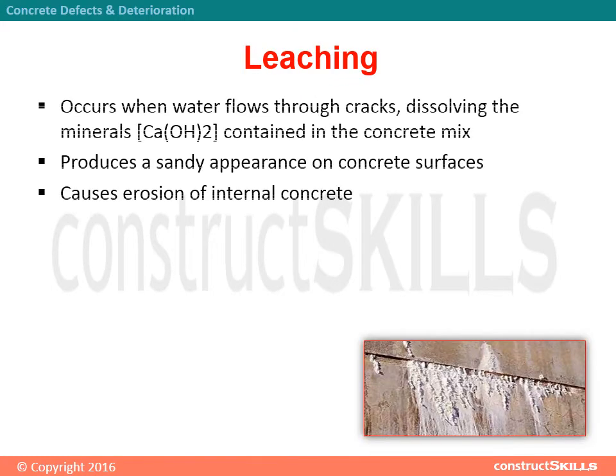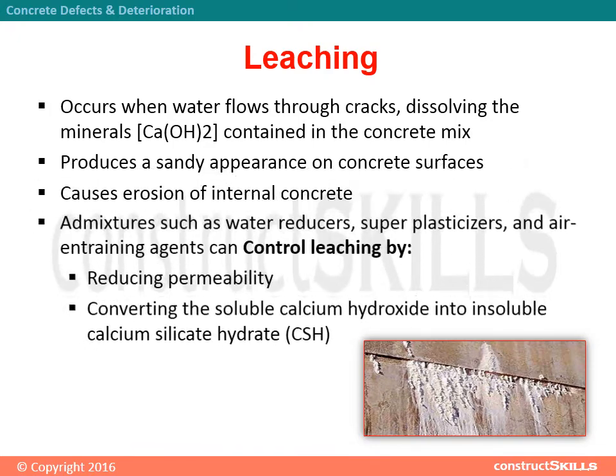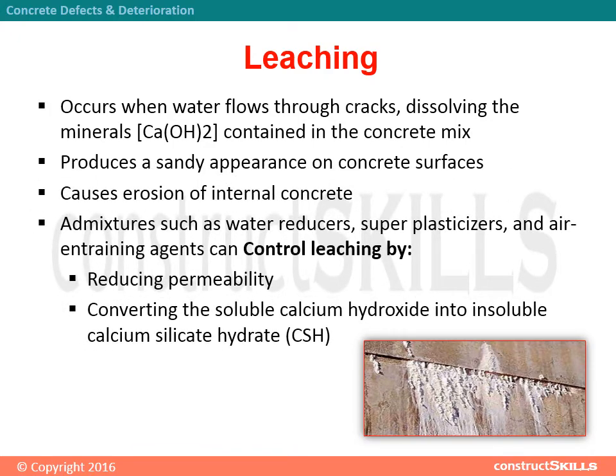Leaching occurs when water flows through cracks, dissolving the minerals contained in the concrete mix. It produces a sandy appearance on concrete surfaces and causes erosion of internal concrete. Adding mixtures such as water reducers, superplasticizers, and air-entraining agents can control leaching by reducing permeability and converting the soluble calcium hydroxide into insoluble calcium silicate hydrate.